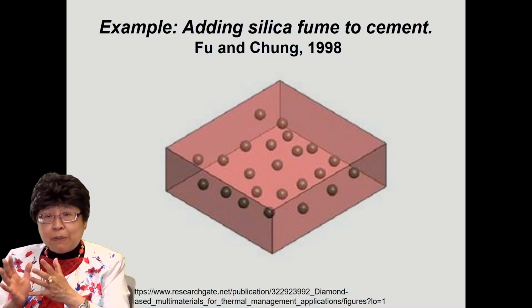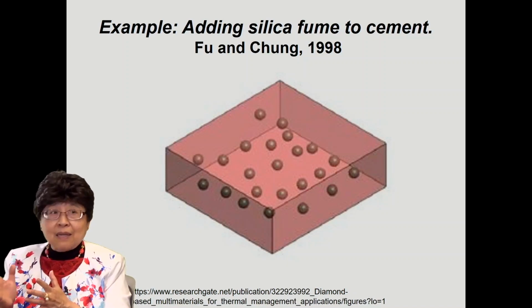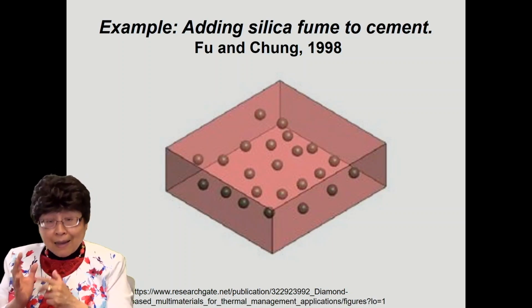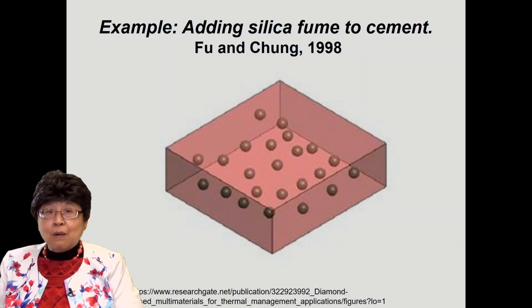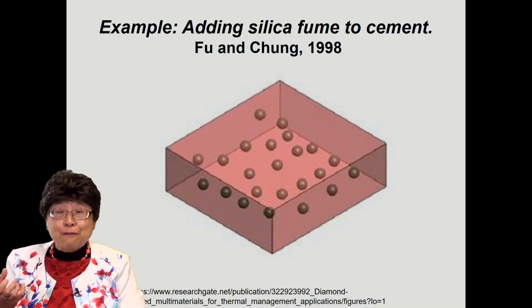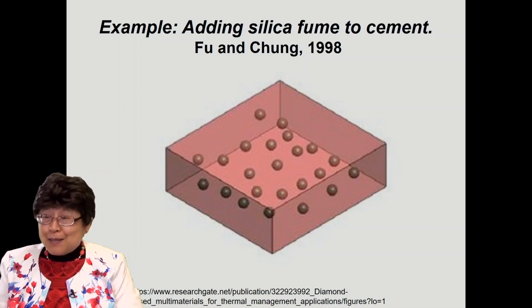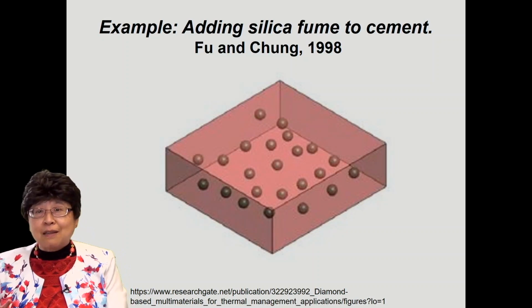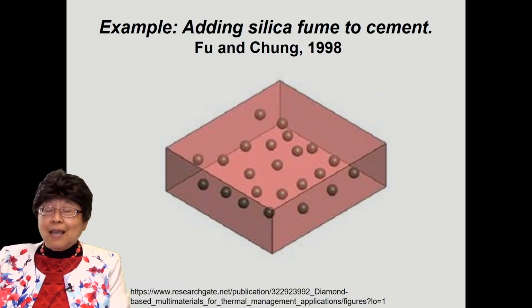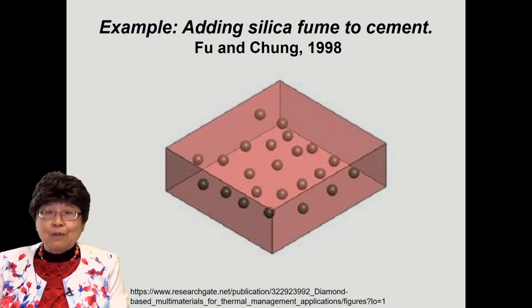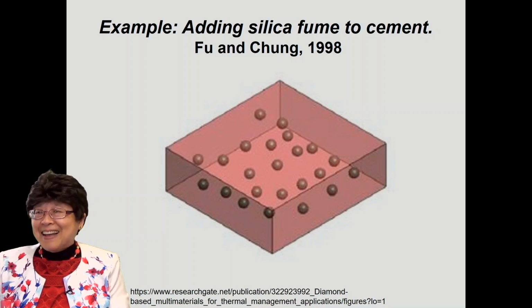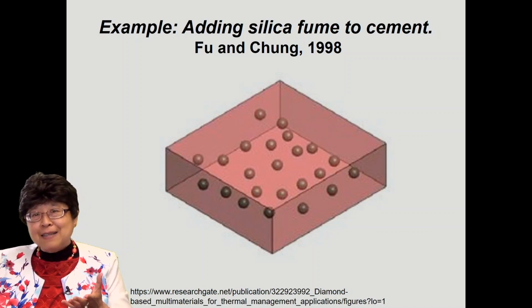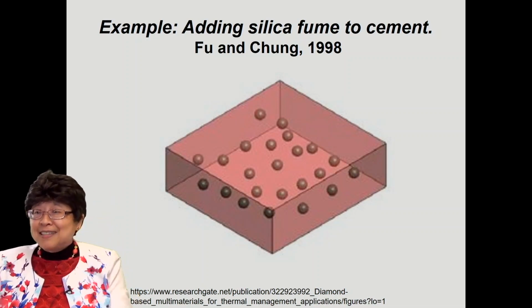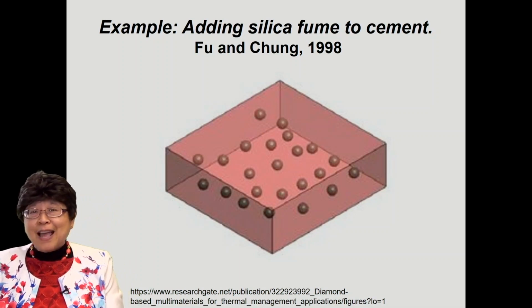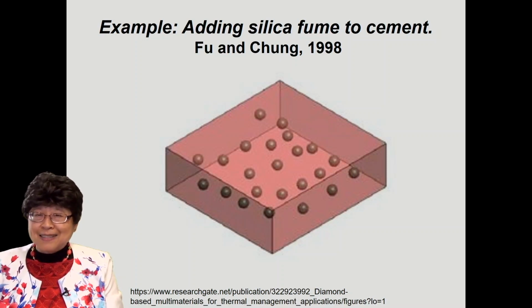And because of the plentifulness of this interface between the silica and the cement, one has enough interface for the interface-derived viscoelasticity to be substantial. But at the same time, the silica fume acts as a reinforcement, making the cement stiffer. So the addition of the silica fume makes the cement stiffer. In addition, it makes the cement more able to dissipate mechanical energy. And having both the stiffness and the mechanical dissipation ability enhanced is something that the scientific community had a hard time accepting when I presented that in 1998.